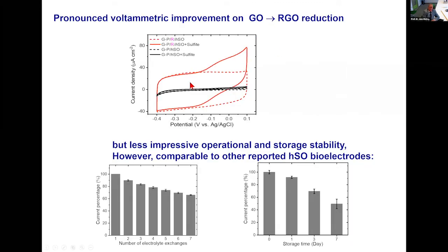And here's what you can see. No reduction, that means still graphene oxide, no voltammetry except for capacitive voltammetry. Then you reduce all the graphene oxide to graphene, and then you get rather nice voltammetry. For an enzyme, it is quite nice, but there are still problems with stability. Every time you change the solution, you lose some of the activity. Whether it is leaking or denaturation is maybe not exactly clear. You can store it, and it's still alive after 7 days, but it has dropped quite substantially. Unless you're going for a biosensor or a biofuel cell that is one-time use and then thrown away, this has to be improved.